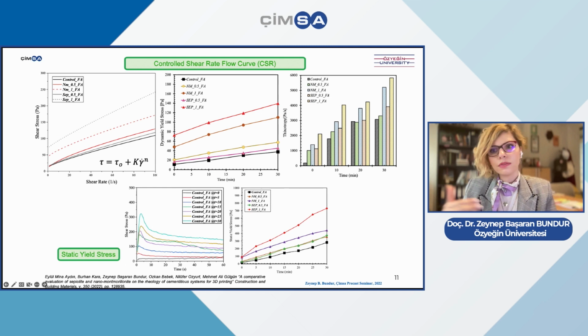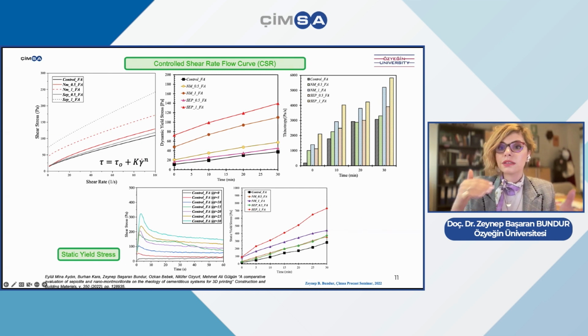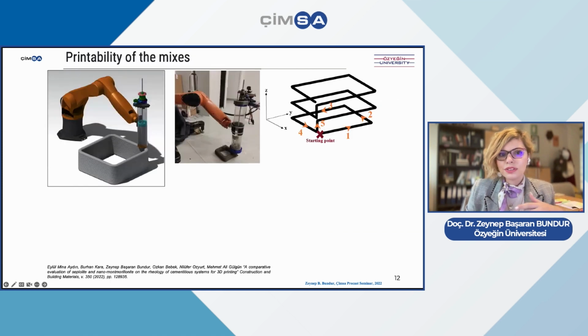But what's important here is the flow curve, which is actually a very important factor in determining the quality control and alignment of this material, because it has to do with being able to extrude the materials. And here we looked at, therefore, the shear stress and dynamic yield stress and the thixotropic values as well. And we see here that this is actually acting as a viscosity controlling agent, and the printing can therefore be carried out step by step and layer by layer.